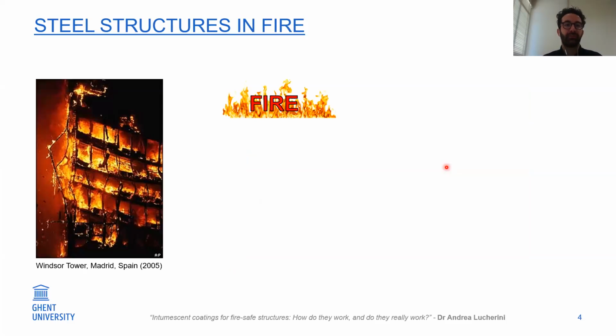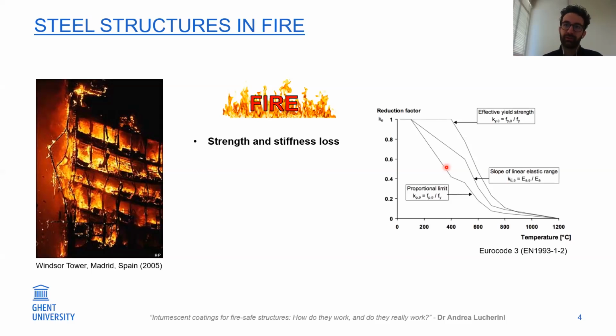And for sure, one of the challenges would be fire. This is an example from 2005, the Windsor Tower in Madrid. When a steel structure is exposed to fire and high temperature, it usually experiences a strength and stiffness loss. For example, if you check Eurocode 3 at 600 degrees, which is not such a high temperature for a fire, since we usually expect 1,000 to 1,100 degrees, you can expect about a 50% decrease in effective yield strength compared to ambient temperature.